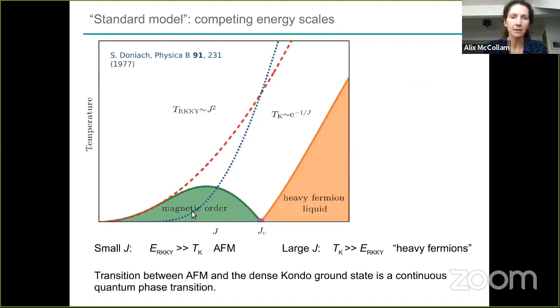This is the magnetic order. I'm going to think primarily about antiferromagnetic order, and then the heavy Fermi liquid, where you have the Kondo effect well established in this part of the phase diagram. And this is, again, this coupling J between the conduction and the F electrons. So at small J, you have the antiferromagnetism dominating, or order, in this region. And then here you have the heavy fermion system.